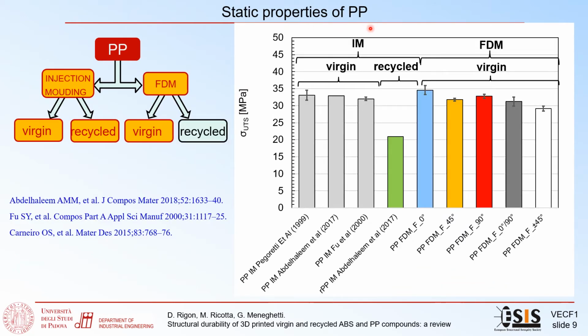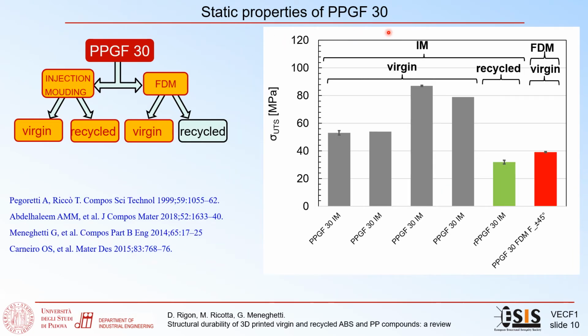Regarding the static properties of polypropylene, here we have the synthesis of the results. By analyzing the injection molding, the recycled polypropylene has a 30% lower UTS than the virgin material. Comparing the virgin polypropylene produced by injection molding and FDM, no difference can be observed in terms of UTS, but if we analyze the virgin FDM, we can see a slight influence of the raster orientation on the UTS, where the best performance was obtained with a raster orientation of 0 degrees, and the lowest was obtained at plus minus 45 degrees.